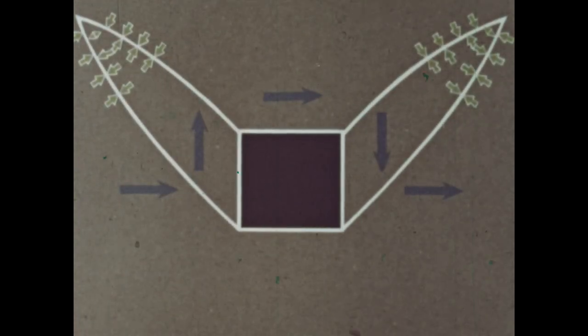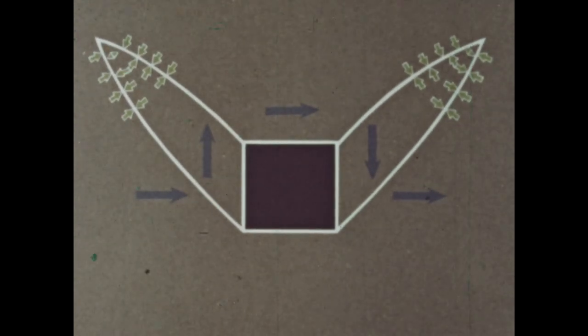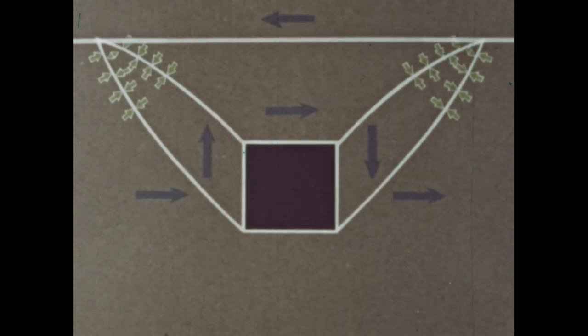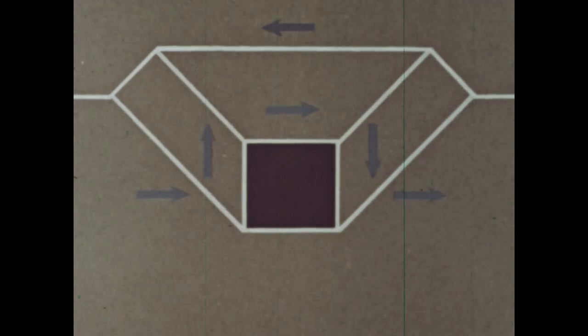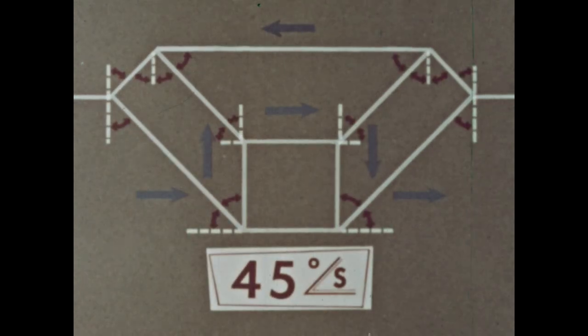Now let us see what happens when a primary domain wall intersects such spikes. The spikes attach themselves to the wall and form a secondary domain structure that eliminates the magnetostatic energy which was concentrated at the tips of the spikes. This happens because the walls all make 45-degree angles with the magnetization vectors whose normal components are now nearly continuous across all the walls.